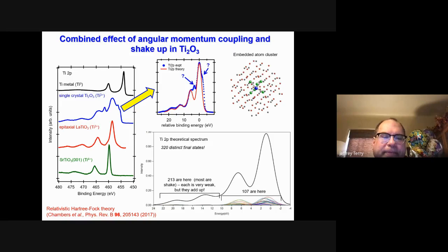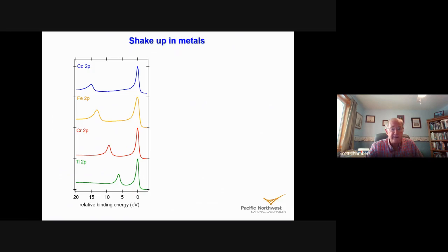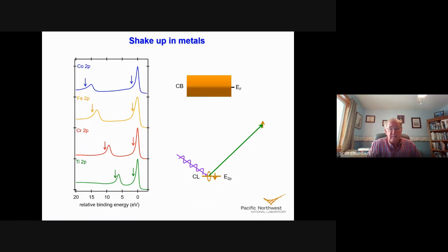Definitely. All righty. One other thing about shakeup: it can happen in metals in addition to oxides. Here are 4 different transition metal 2p spectra. You notice that all of them have a little asymmetry on the high binding energy side of each spin orbit peak. The reason is that these are metals, and so you have a partially filled conduction band. You can have these many body excitations in the final state, but you have a continuum of possibilities.